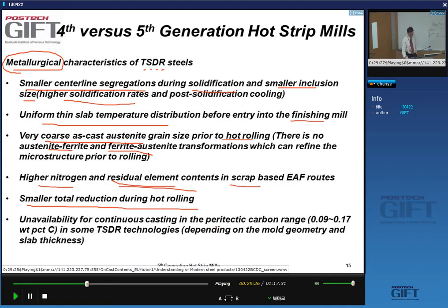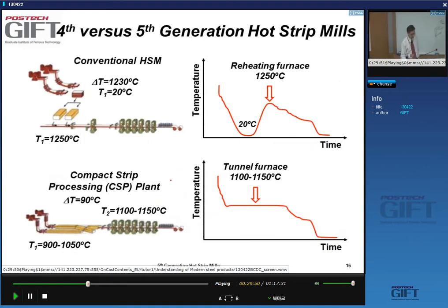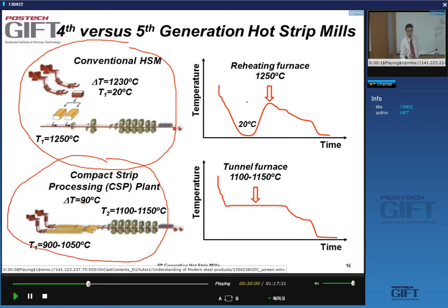Right, and there are some difficulties in continuous casting for peritectic compositions, but I think that these things can be addressed in practice. But as you know, peritectic grades do give you problems, and they're a little bit more serious in the case of this compact strip processing. So this is a big difference here between a conventional system and a compact strip system: you do not cool to room temperature. You go straight from the caster into a tunnel furnace, yes, where you homogenize the bar, and then you do the hot rolling.